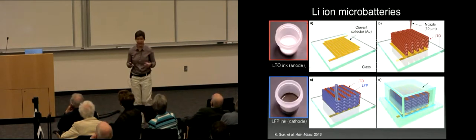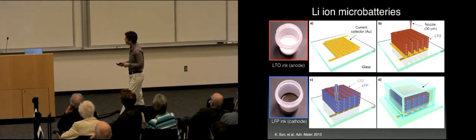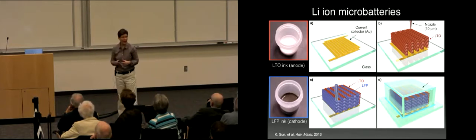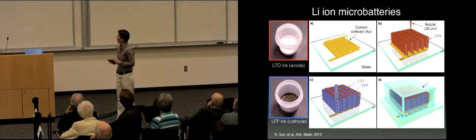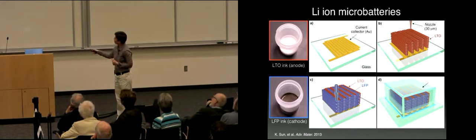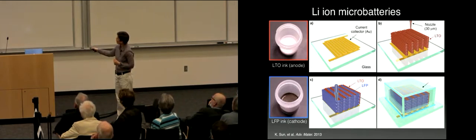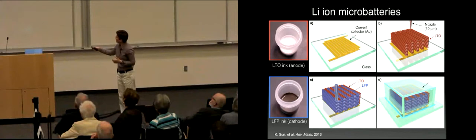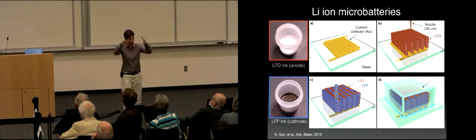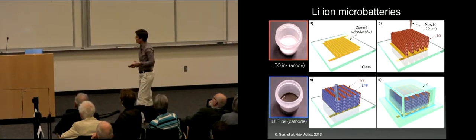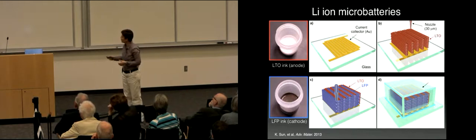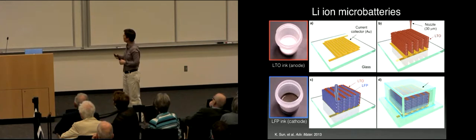The way we did it is we made two inks, very pasty-like, toothpaste-like inks. One is called an LTO anode, lithium titanate oxide. This one is LFP, lithium iron phosphate. This material is the cathode, and this material is the anode. We have first deposited gold contacts on glass. These are interdigitated electrodes. These are the current collectors. On each of these interdigitated teeth, we're printing an anode and then the cathode. And then you'll see we package that battery. We encase this in this first generation design of plastic case. It's filled with liquid electrolyte through which the lithium ions and the electrons move.